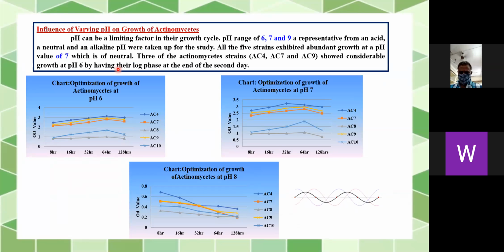Influence of varying pH on growth of actinomycetes. pH can be a limiting factor in the growth cycle. pH values of 6, 7, and 9 were taken for the study. All 5 strains exhibited abundant growth at a pH value of 7, which is neutral. 3 of the actinomycetes strains, AC4, AC7, and AC9, show considerable growth at pH 6, having their log phase at the end of the second day.